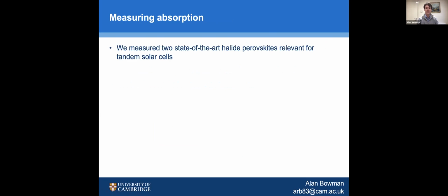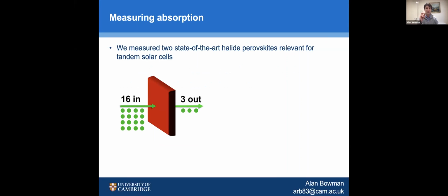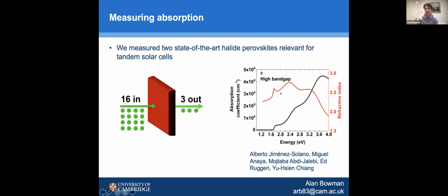So we went into the lab with state-of-the-art halide perovskites, and to measure the absorption, it's a very easy experiment fundamentally. You just count the number of photons hitting the material and the number of photons not being absorbed by the material. And from that, you can get out something that looks quite complicated like this at first glance.